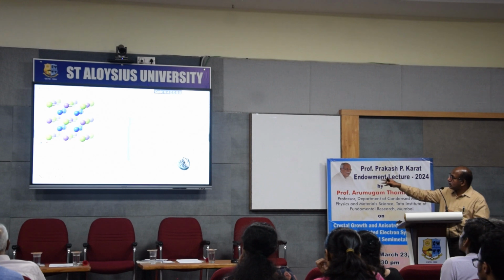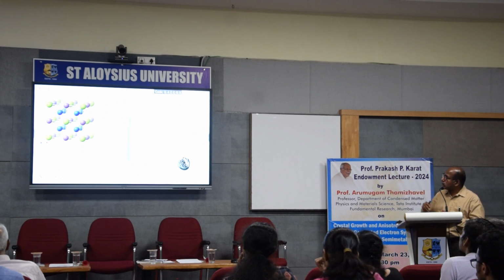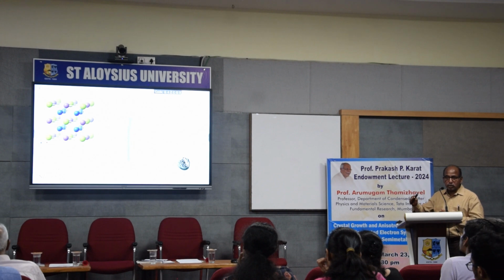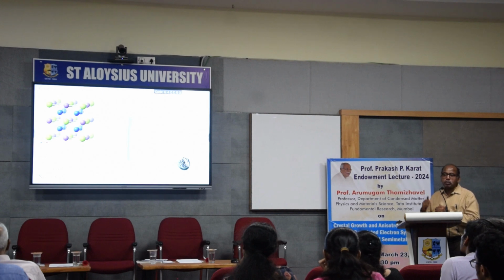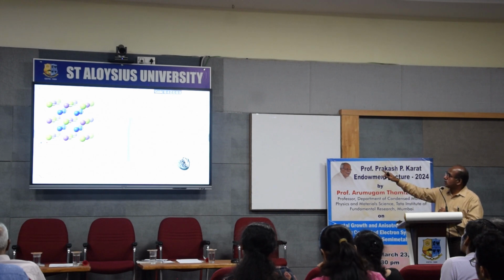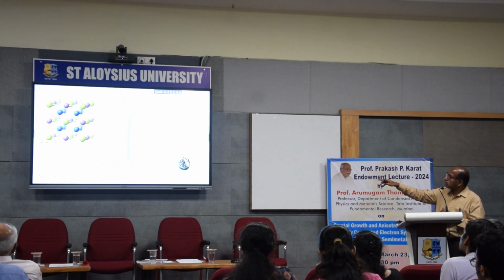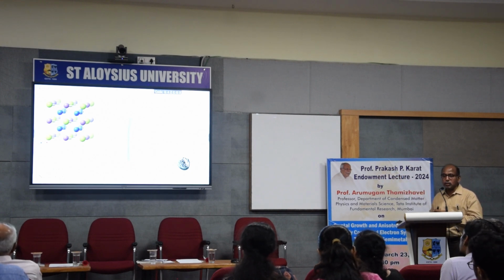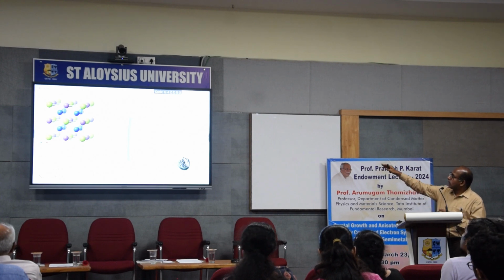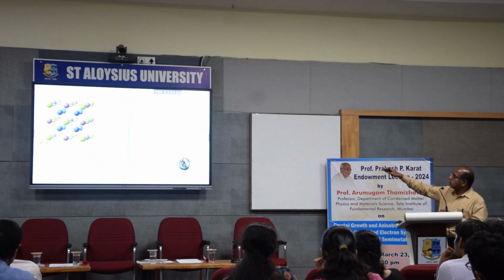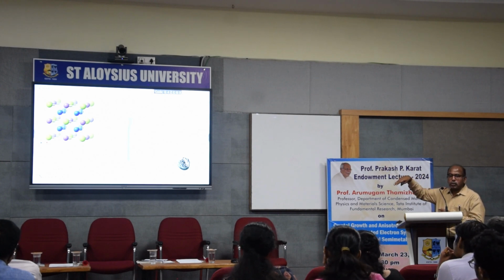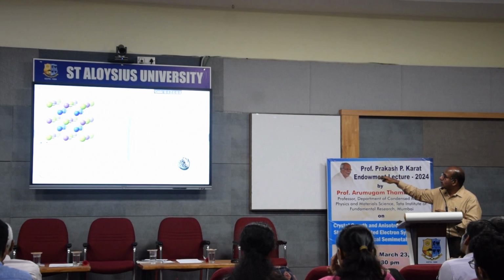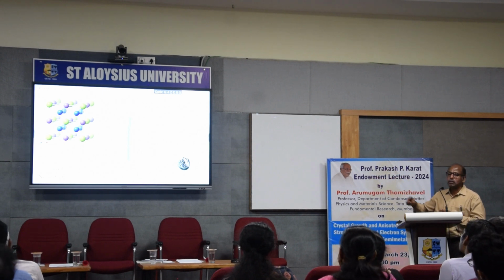The material to be crystallized I have taken in a sharp tip alumina crucible, which is sealed inside a molybdenum tube. And this molybdenum tube is further sealed in a quartz ampule, because at elevated temperature, metals get oxidized. So this molybdenum will get oxidized if I don't use a quartz tube. So that is what is happening there. Inside the molybdenum crucible, we have the alumina crucible, inside which we have cerium and magnesium. And I did the temperature profile like this, from 0 to 800 degrees centigrade in about 72 hours, and then kept it there for 24 hours. And by slowly cooling it, I got this, the bottom one, which shows that.